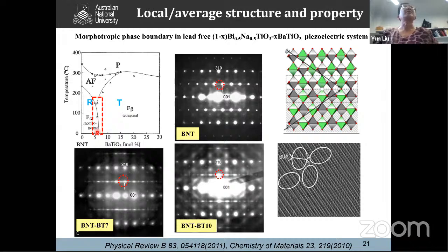In the past, they said, oh, that's a phase boundary, so you must have a two-phase mixture. But if you physically make a mixture of these two phases, you will never get this property. So it's not simply a two-phase mixture. In previous research, when they used X-ray powder diffraction to identify the average structure, they found it is monoclinic. But from a crystal chemistry point of view, if you consistently change the chemical composition, you cannot have a low symmetry crystal structure in between two high symmetry crystal structures.